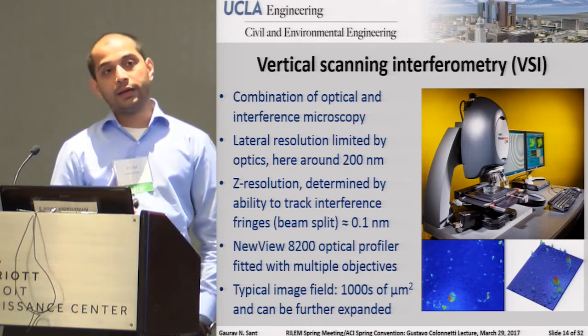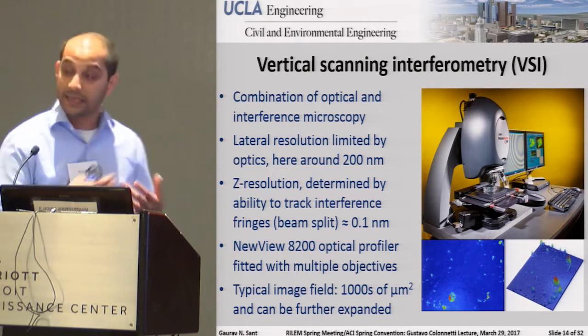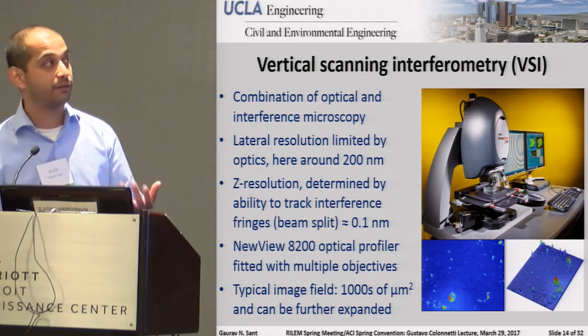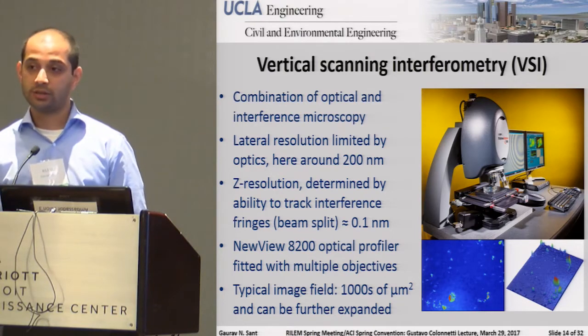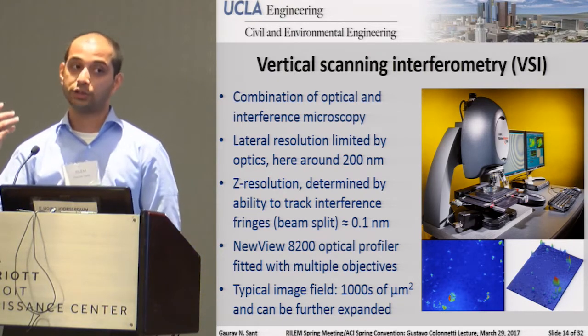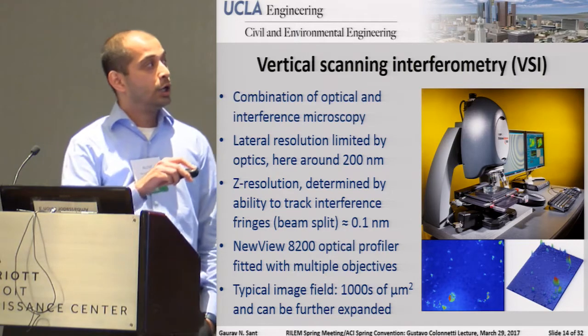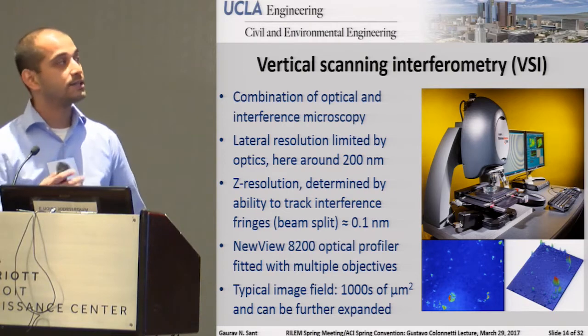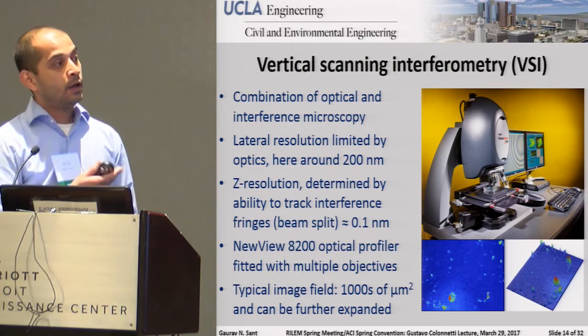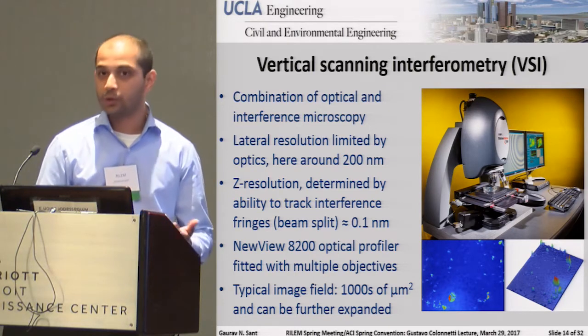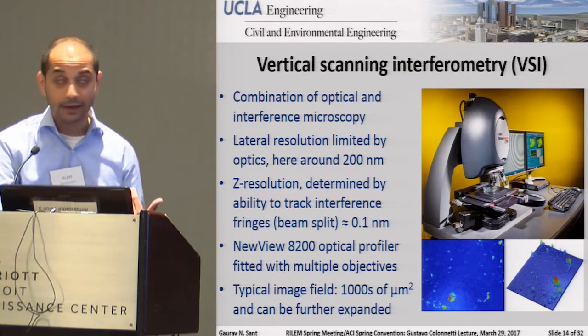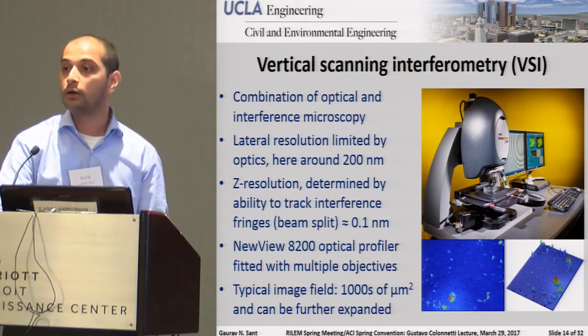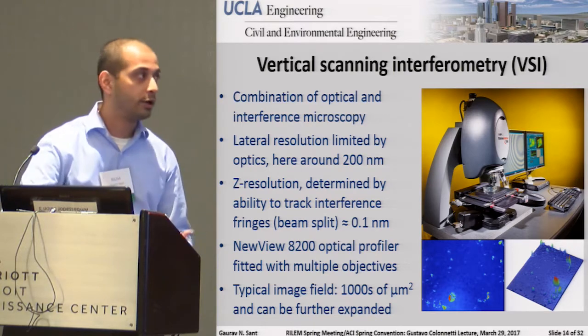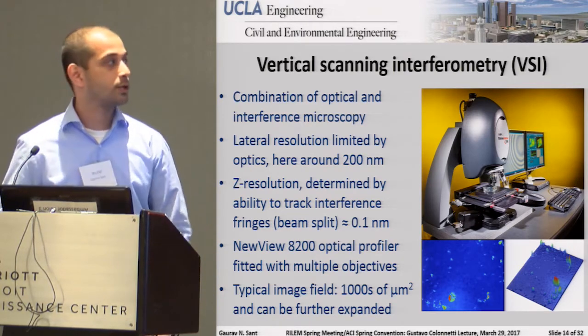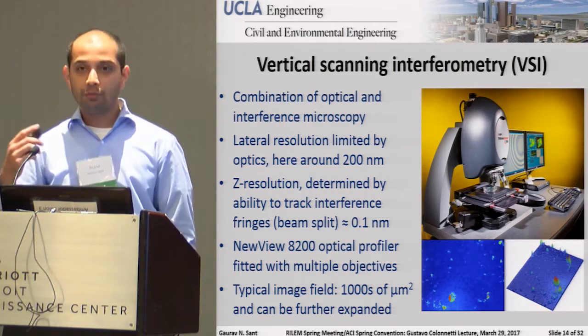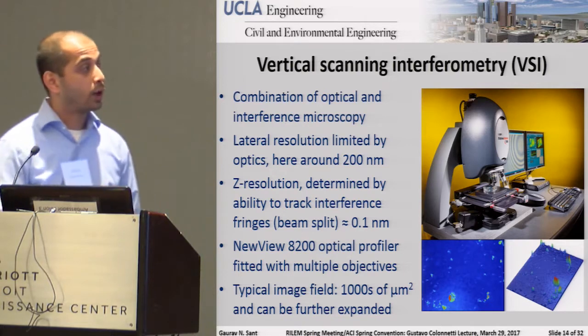Now, the nice thing about doing interferometry is if you couple it with an optical microscope, you can, of course, see the X and the Y, as you usually would under high magnification. But you've got a beam of light which you shine down on the surface. So as you shine the beam of light on the surface and you get the reflection back, since you've got a reference that's associated with it, you track the movement of the interference fringes. And the nice thing about the interference fringes is because you're looking at beam splitting, depending on whether you have constructive or destructive interference, you essentially null the signal or you amplify it. But the nice thing about this is you can resolve this theoretically to about one angstrom. Practically speaking, in a thermostated laboratory, you're probably much closer to about 5 angstroms, not 1 angstrom. But nevertheless, you've got tremendous resolution in the Z direction, which is quite good to have.